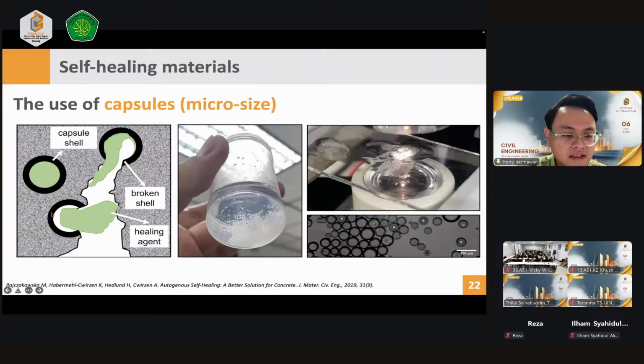So if you see from the picture on the right hand side, we preserve the healing agent inside the capsule shell, and imagine we incorporate these capsules into the concrete materials, and when cracks come into the concrete, some of the capsules will break, and it will release a sufficient amount of the healing agent to the surrounding environment of the crack. And in this case, later, either a healing or sealing process will take place.